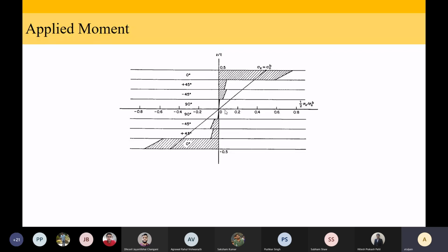So this also tells us why we should have stiffer materials at the top and bottom and less stiff materials maybe at the center. If the 0 degree was in the center, the amount of stress it would get would be only this much, perhaps, if this was 0 degree. But by putting 0 degree at the top, the amount of stress value is much, much higher.